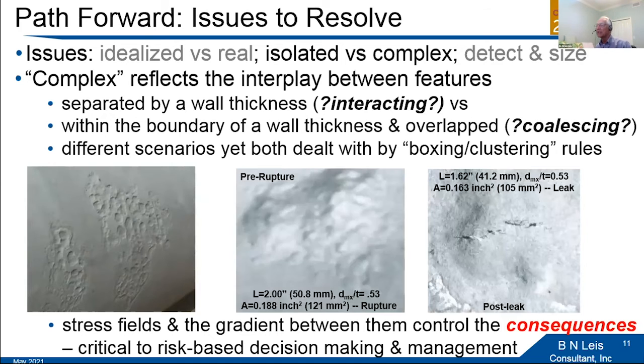I'm adding two plots or two charts to this, which show a feature very similar to what you see in this image here, where we have overlapped pits, and you can see here's a pit and here's a pit. These are really pits within pits. You see a lot of little pits here. These pits are growing by virtue of smaller ones giving rise to a bigger one. This is not quite a full wall thickness. It's a significant barrier, if you will, between this feature and this feature coalescing or failing in a shared way.